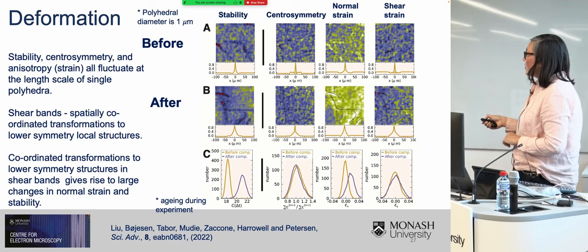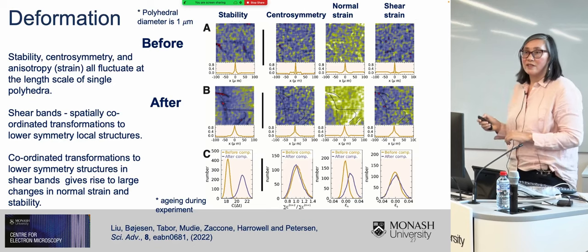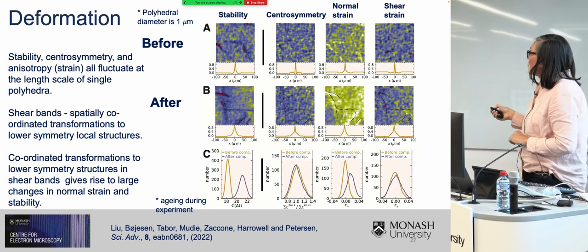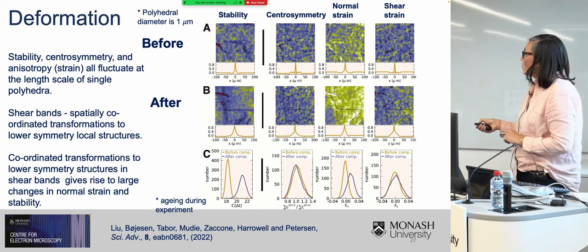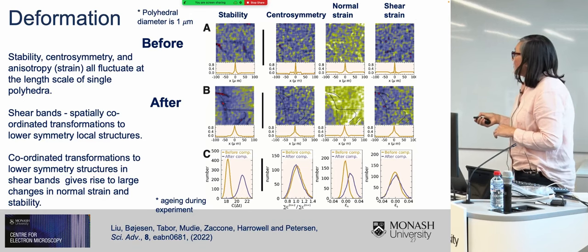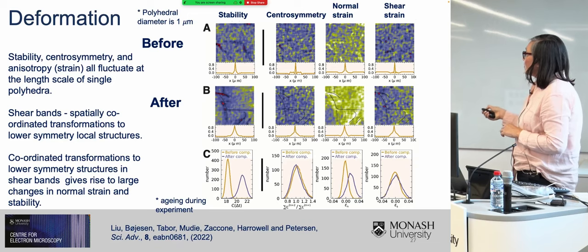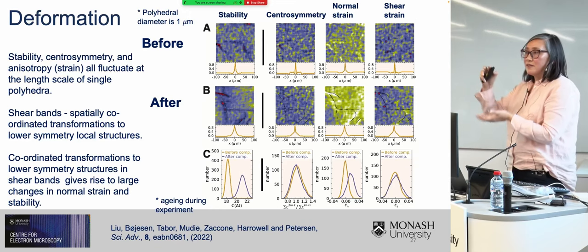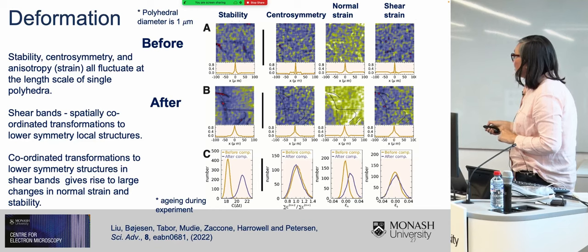The diameter of each coordination polyhedron is actually 1 micron. And so you can see immediately that all of these mapped parameters actually fluctuate at the length scale of a single polyhedron. However, and this is reflected in these autocorrelation functions, when we compress the glass, so induce deformations within it, you can see that these correlation lengths are actually increased. And that's because we have the appearance here of these shear bands.